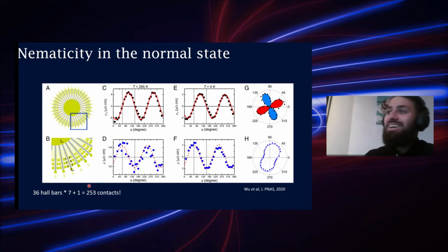But the results were quite nice, because they found that there is a resistivity anisotropy in the plane that does not correspond to the crystalline axis. So this was a truly electronic nematicity.